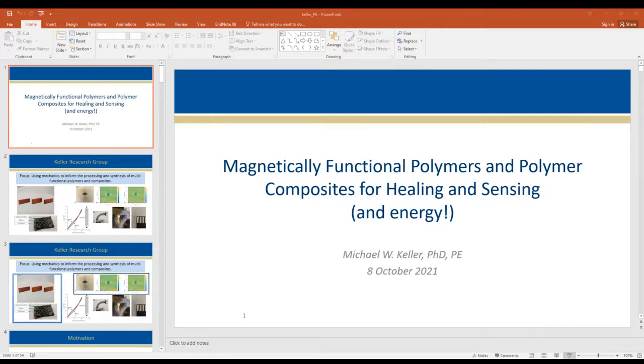We're working on trying to get it to a polyurethane, but the thermal stability of the polyurethanes that we have easy access to has been challenging. So what we did here, the grad student built this interdigitated network where we could flow part A of a healing chemistry through one channel and part B through the other one. We depolymerize it, so you can see this is prior to depolymerization, and you can see that white PLA that's in there. Then it becomes fairly clear.